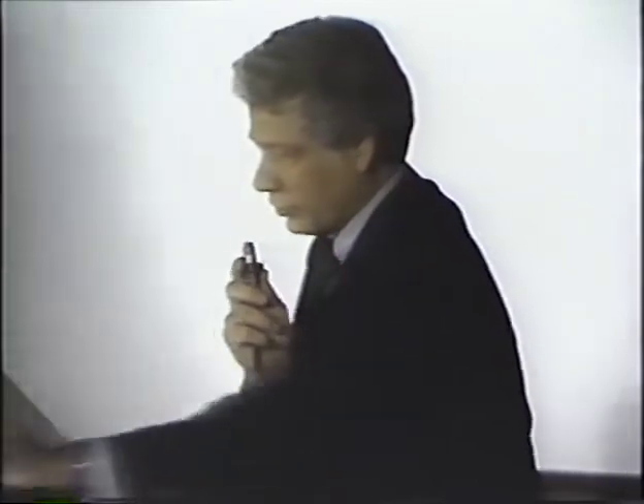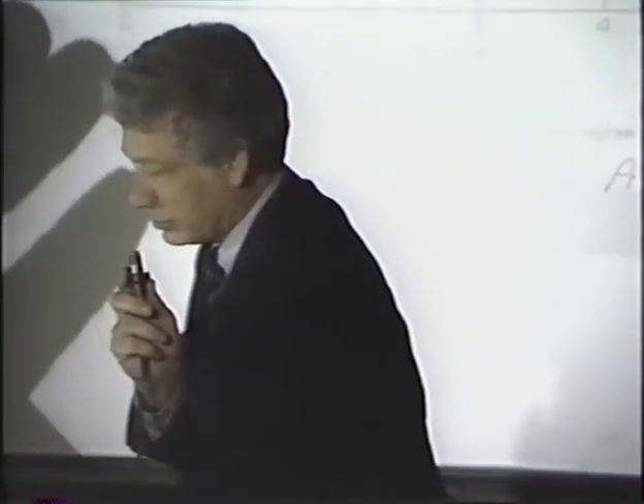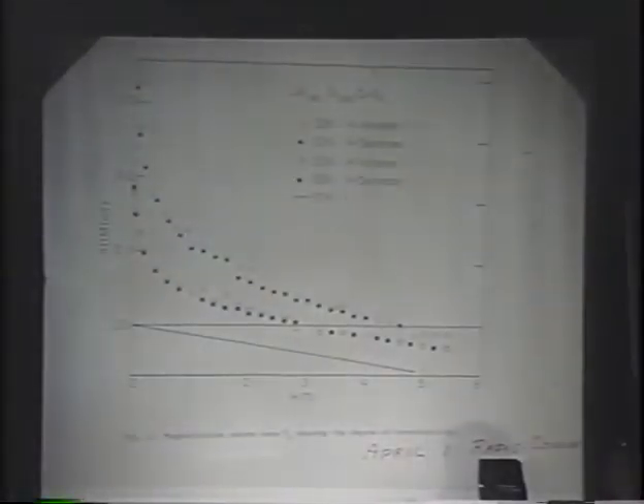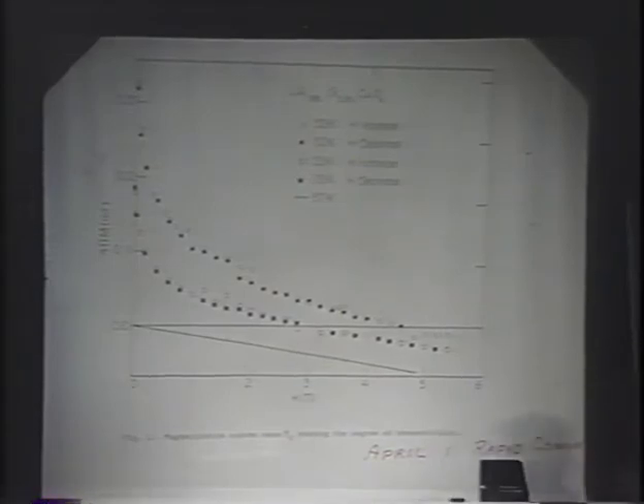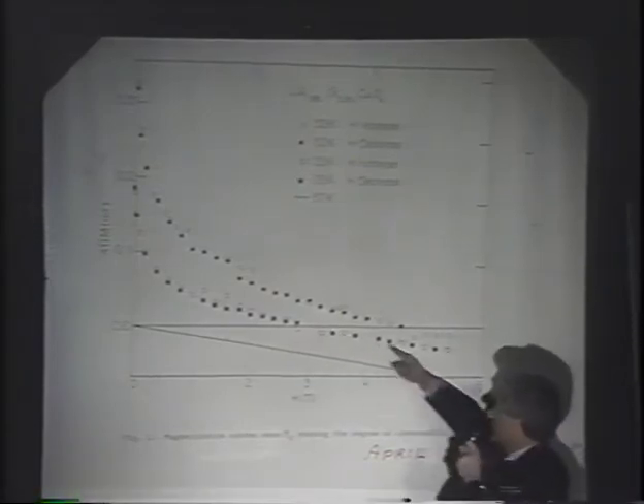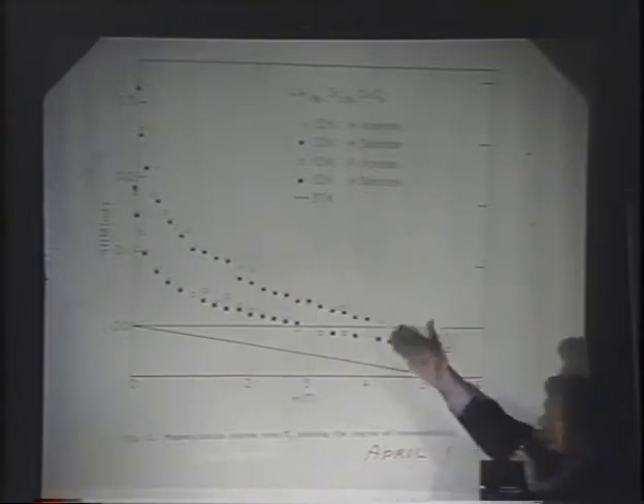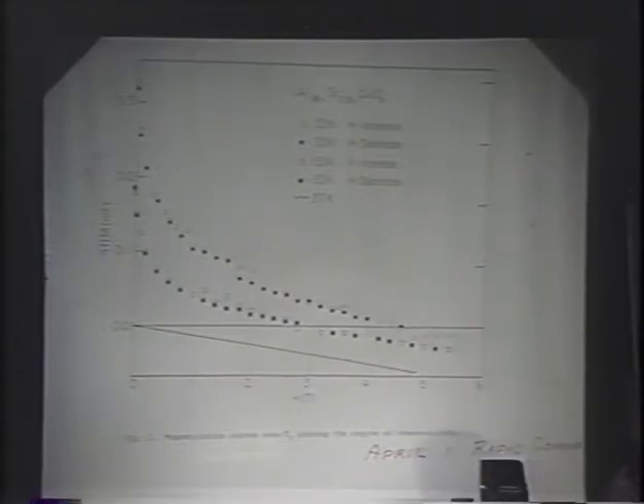And in the lanthanum strontium, it's extremely reversible. 4 pi M is a function of H. The open circles are increasing field, decreasing field, and you can get the free energy out of those data, and it's published as a rapid communication April 1. You can look all those data up.